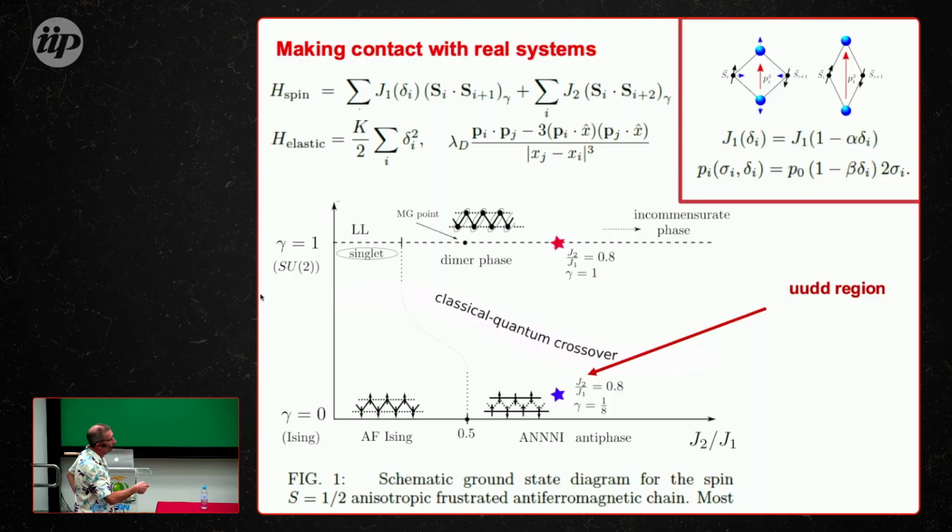So here I broke SU2 invariance in the magnetic part, and it's even closer to experiments. The dielectric part is Ising, so let's keep it Ising. As for the magnetic part, I started with SU2 because this is what I knew when I started. But then we said, okay, let's consider a more Ising-like magnetic part. This is motivated by the experiments because they see important crystal fields. And indeed, taking into account this easy axis crystal field term, you get this up, up, down, down magnetic ordering.